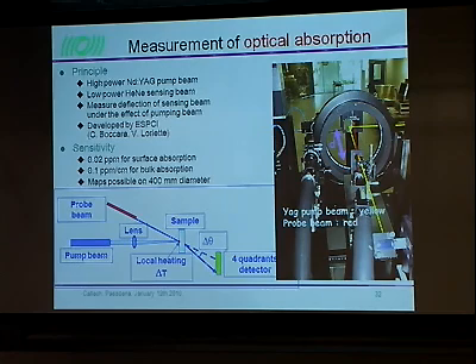So basically by measuring the deflection of the sensing beam through the thermal gradient which is induced in the coating by the high power beam, we are able to measure losses as low as a fraction of a ppm in terms of surface absorption, at the level of 0.1 ppm per centimeter for bulk absorption. This is one of the instruments we use to study the coating.